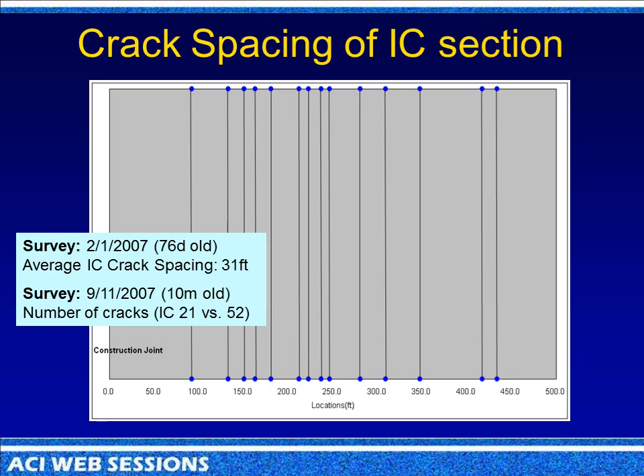They also did a crack survey of this particular section. They pulled out a 500-foot section. And at 76 days, some of the, Victor, I believe, is a room, and a few other people went out and did this whole thing. They found the crack spacings were 31 feet. The DOT says their normal crack spacings are about 5. These are real micro hairline cracks at about 3 to 5 feet. So they instantly noticed a difference.